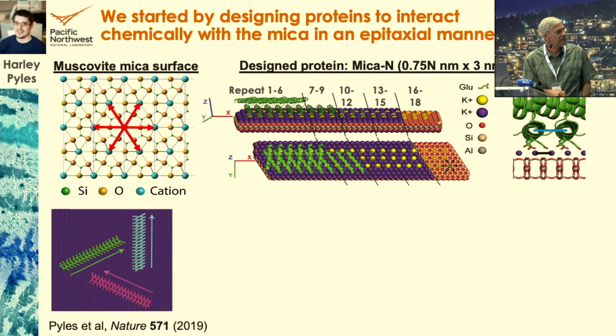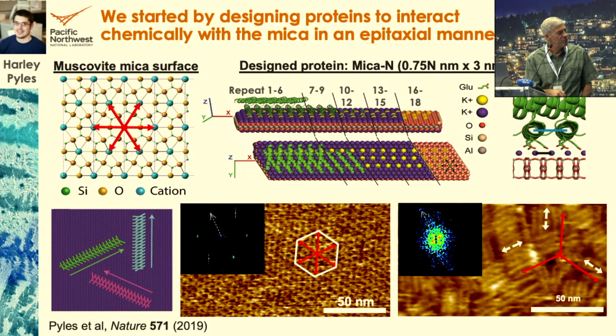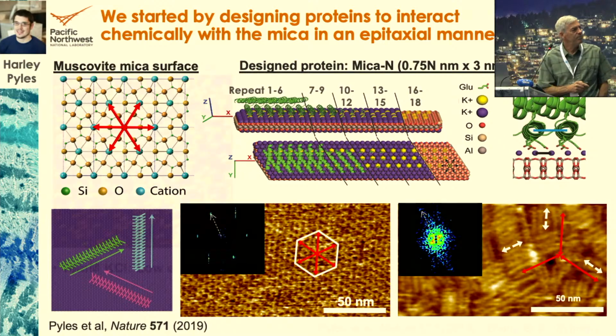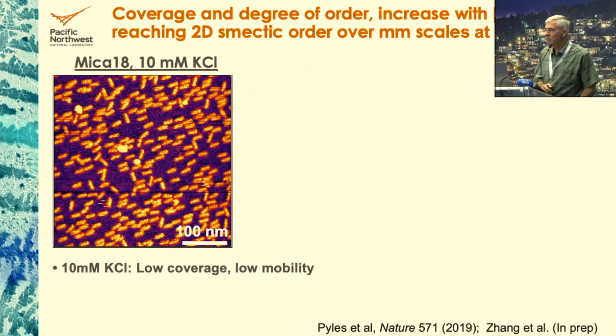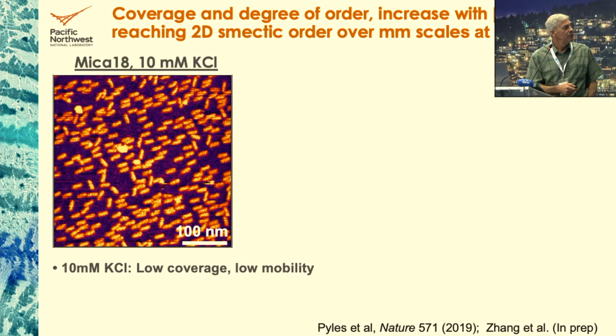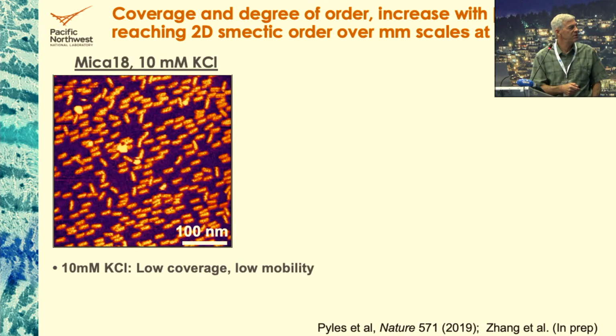And so we expect that these things will bind along 3 directions on the mica lattice. Here's the AFM image of the mica lattice, and here's the protein on top. And indeed, you can find proteins lying in all 3 directions. But it's not that simple. What we get depends on what the solution composition is, what electrolytes are in the solution. So at a low concentration of potassium, we find that we just have proteins bound to the surface.